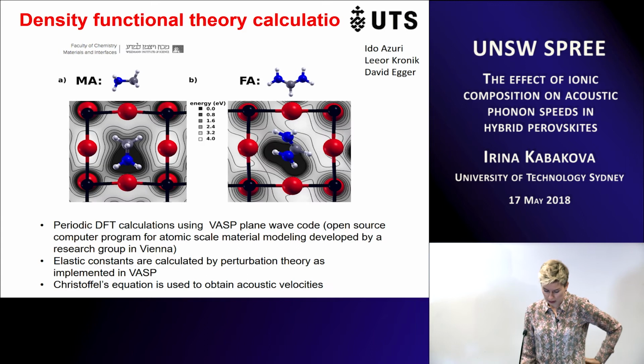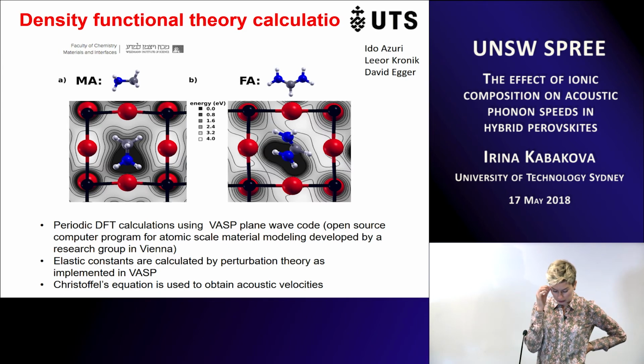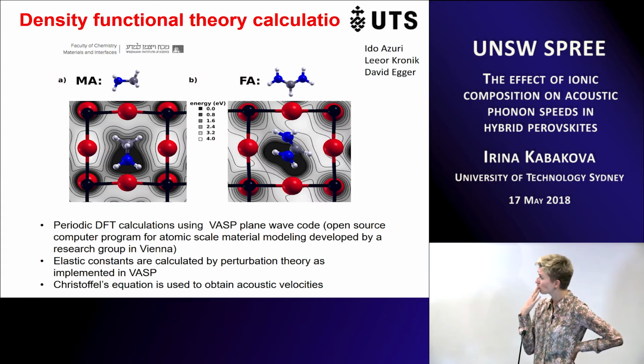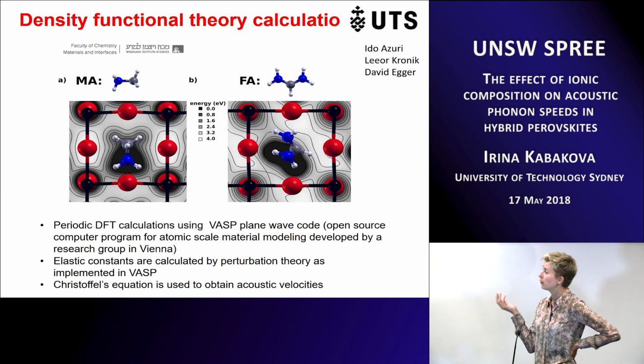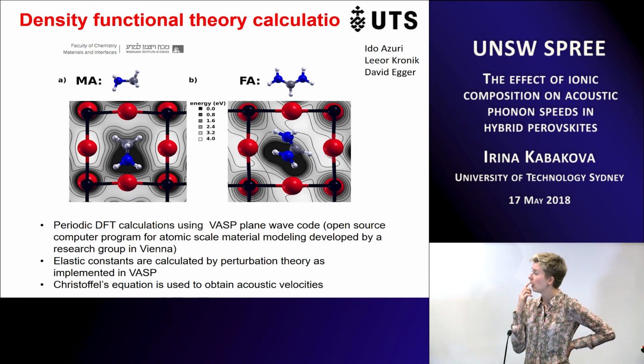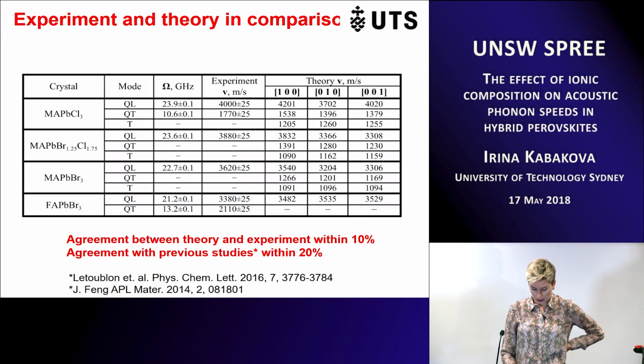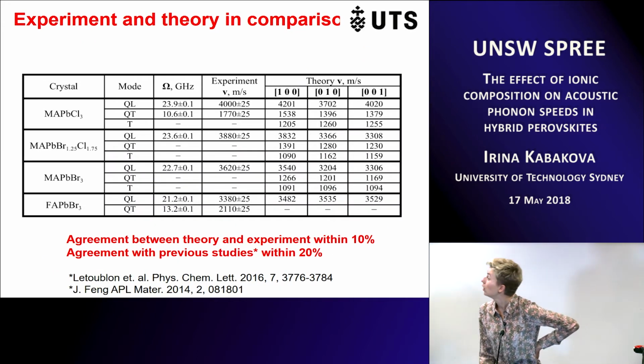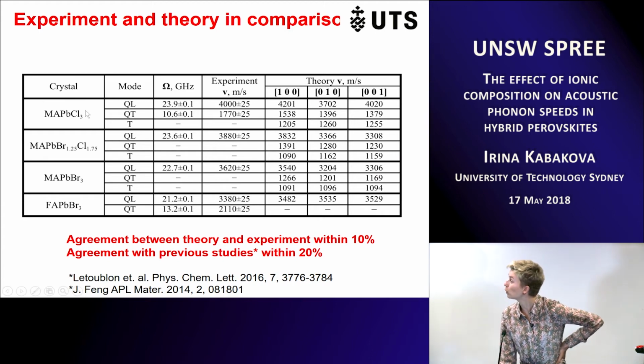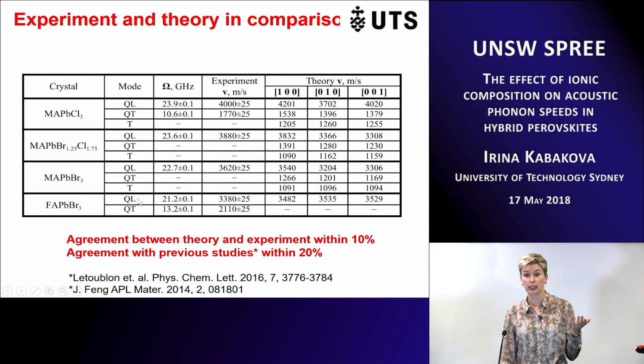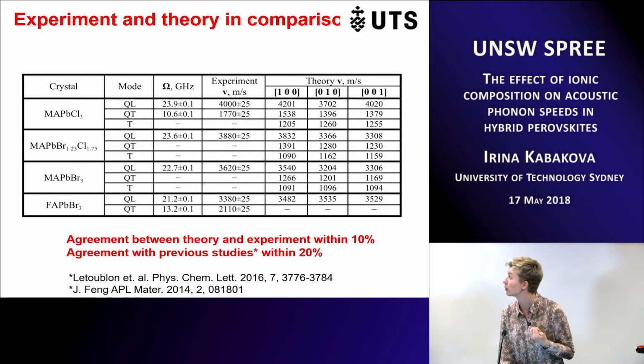So here you see a calculation for MA and FA crystals, and then using perturbation theory in the same calculation package. The package is an open source program developed in Vienna and available for everyone. You can calculate elastic constants. And this is a result of the calculation. So you see our 4 hero materials, and these are the 3 acoustic waves that we expect to obtain in these materials: quasi-longitudinal, quasi-transverse, and transverse.